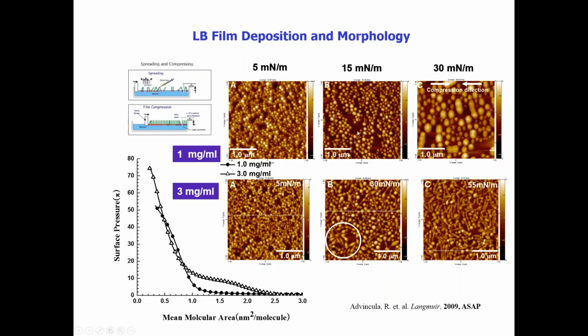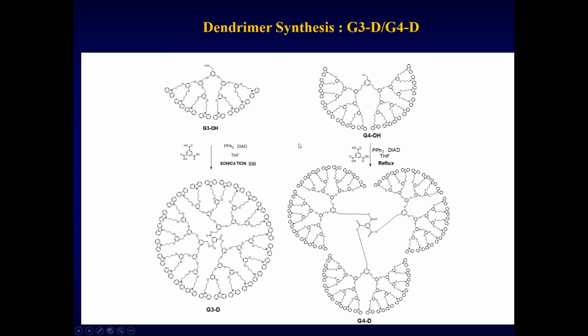Now, since these dendrimers are actually electrochemically active, and I'll explain to you in a little while why we are very particular with this reactivity, these carbazole units can link up with the neighboring carbazole units to produce polycarbazole, and this can be done electrochemically. So in this case, once we prepare films of various concentrations or packing, we can pattern them using electrochemical nanopatterning, which I covered in my previous webinars, using a conducting AFM tip. We have these films prepared on an ITO substrate, and then we move the tip. In this case, it's very clear the term UH was patterned on this LB film.